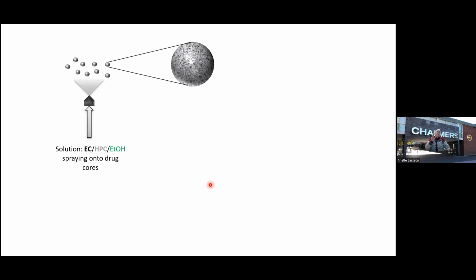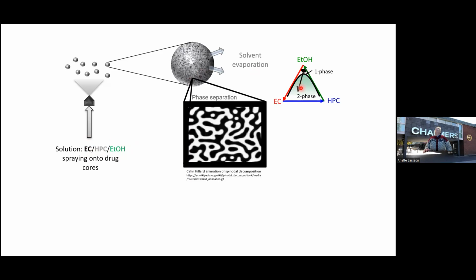So if we apply this now for this system where we have a spray solution that contains the two polymers and the ethanol, we spray it, and the solvent evaporates. So we start in the one-phase region, enter into the two-phase region, and we get the phase separation. And in this phase separation there can be different types of phase separation. Here is an illustration from Wikipedia on spinodal decomposition.